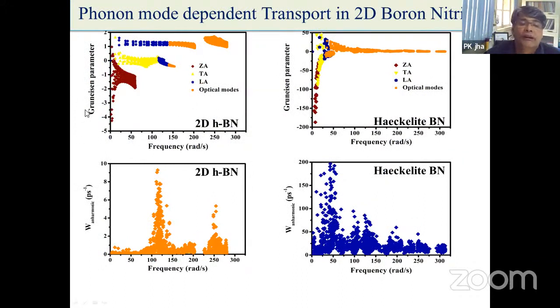Then the Grüneisen parameter for Haeckelite and the 2D hBN, then it is the anharmonicity. You can see here, right? So the anharmonicity is lower in the case of 2-dimensional hexagonal boron nitride in comparison to the Haeckelite boron nitride, right? Here it is up to 200, you can say. So that means the anharmonicity increases. Therefore, it is expected that the Haeckelite boron nitride will have the lower lattice thermal conductivity.